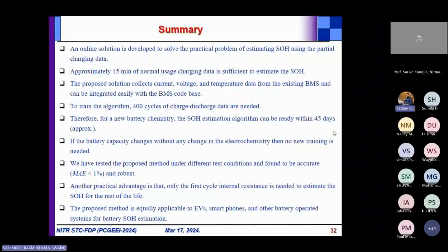Now the batteries we have used here for testing and training have the same electrochemistry. If you change the electrochemistry, say, this battery was lithium cobalt oxide, and you change it to lithium iron phosphate, the same method is applicable. The only thing you have to do is first gather the 400 cycles of data, which just needs 45 days. Then the method proposed here can be reapplied. We have tested it, and as I said, we have achieved mean absolute error less than 1%.